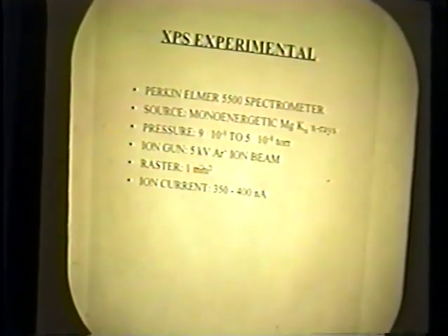The ion gun was a 5 kilovolt argon ion beam with a size of area of bombardment of 1 square millimeter. The ion current was 350 to 400 nanoamps, and this setup for the ion gun produced sputtering of some 2.5 to 5 angstroms per minute.